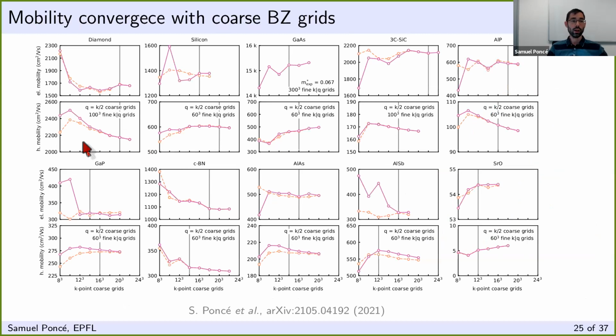So now I want to touch briefly on convergence. What I'm showing here is the electron and the hole mobility for 10 simple semiconductors. I'm showing this as the coarse k-point and q-point grid convergence for a given fine grid. As you can see, the mobility converges relatively slowly with the grids. So you have to go to quite dense coarse grids. And this is the mauve curve.